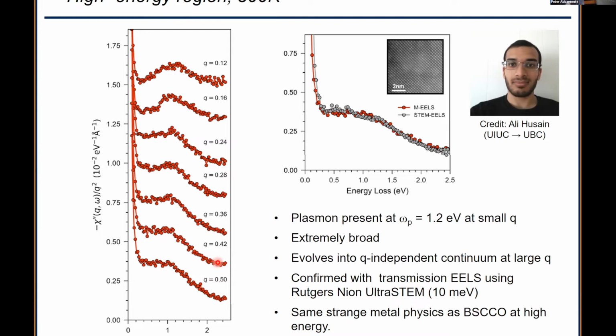People have asked us how we know this is not a surface effect. So we've actually done transmission EELS measurements now, in both this material and in BSCCO. That's a bulk probe, and we can show that you get quantitative agreement. That's actually what's in this plot with transmission measurements. So it's a bulk effect, and it's highly reproducible. We've seen it in dozens of different materials, with multiple different grad students with different PhD theses, different postdocs. So it's highly, highly reproducible.